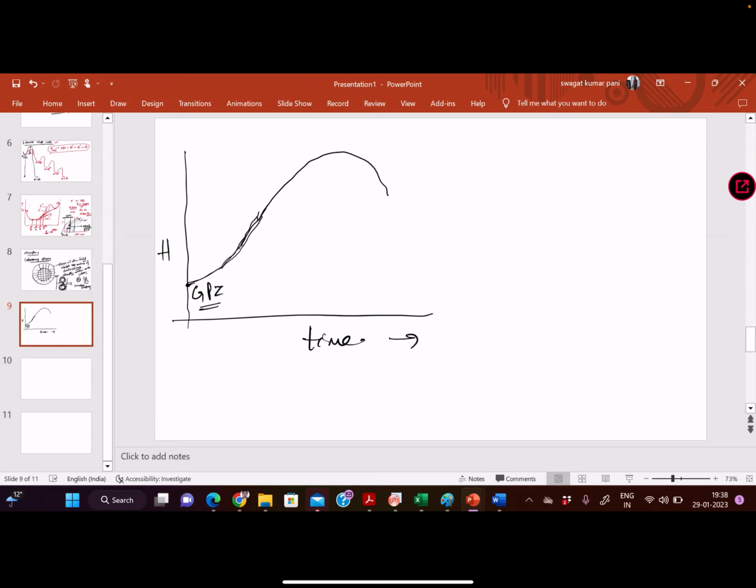Okay, so now we'll see this curve, the hardening curve or the aging curve. Here we have hardness versus time. It looks something like this. Initially GP zones are formed. They are totally coherent, so there is no strengthening. Then as GP zones initially start forming, they are coherent, then as their size increases, the strength increases, hardness increases because of the coherency strengths, as I told.